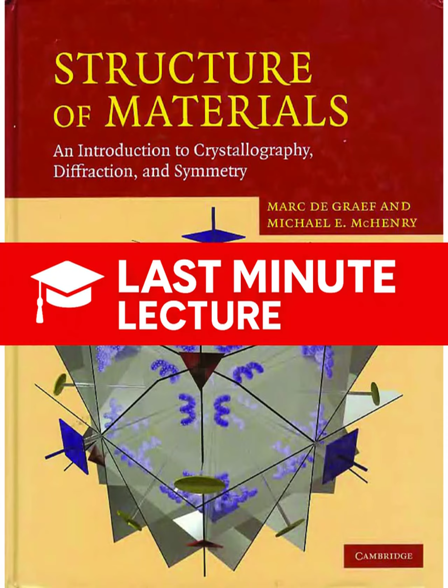It implies that the structure isn't perfectly symmetric. It allows for slight geometric distortion in the tetrahedra, which is key to understanding the various polymorphs of SiO2. But the structure remains stable. Because of Rule 2. Because we move on to Rule 2, the electrostatic valency principle. This states that the sum of the electrostatic bond strengths arriving at an anion must equal the magnitude of the anion's charge. So how does that work for quartz?